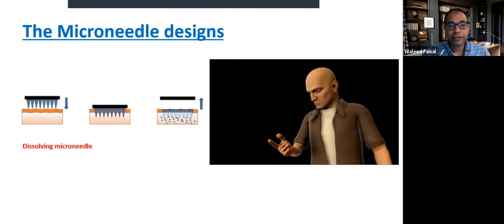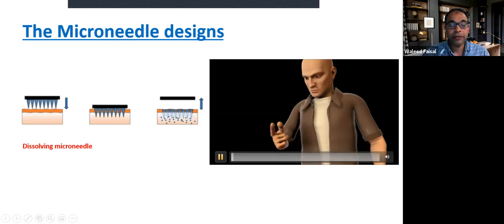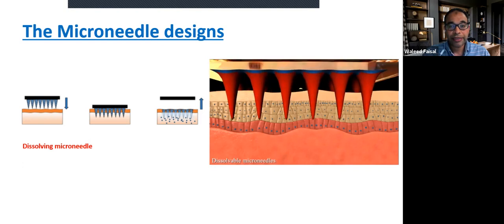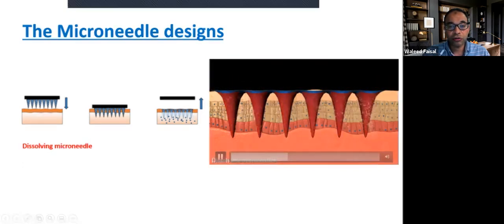The microneedles have different designs, from the old solid design to hollow microneedles, coated microneedles, and dissolvable microneedles. Dissolvable microneedles are the most used technology, where you mix the drug and the polymer in a suitable solvent. After dissolving them, you put the solution in a hollow mold and leave it to dry, and then you collect your needles with an adhesive substrate. Then when you apply it to the skin, it penetrates the stratum corneum, and the polymer starts to dissolve, releasing the medication inside the skin to give the effect of the microneedles.